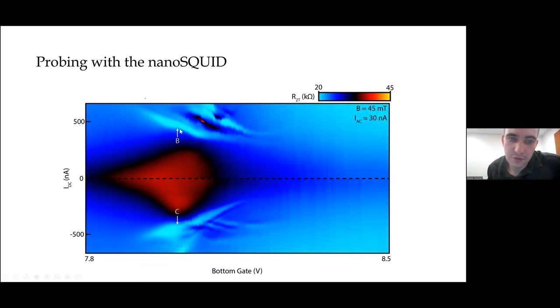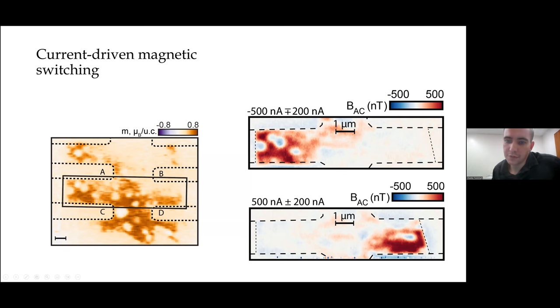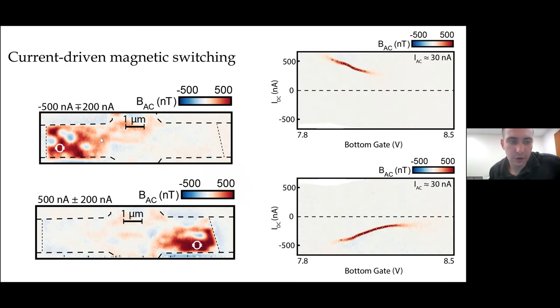We're going to park the DC plus AC current right here, and we're going to take 2D images in the quantum anomalous Hall plateau. This is what we see with the SQUID. This is the region right between these four contacts that show quantization of the anomalous Hall resistance. As we flow current from bottom to top, we see switching of the local magnetic order on one side. And when we flip the direction of current, we see switching of local magnetization on the opposite side of the device. So what's happening is, in phase with the applied current, the local magnetic order is flipping. We can park our SQUID right over these features and then measure the SQUID response as a function of DC current and bottom gate. This is shown on the right side of this plot for both current directions.